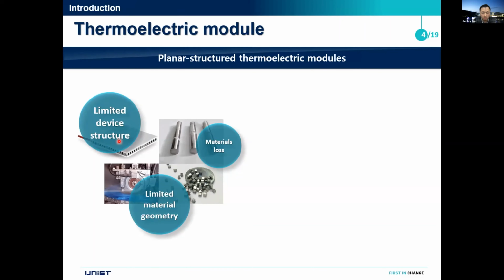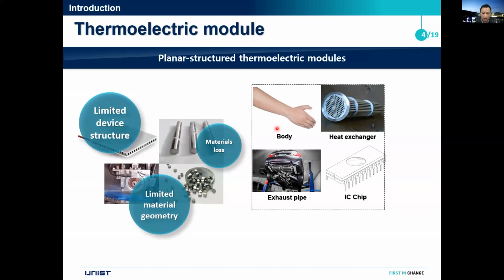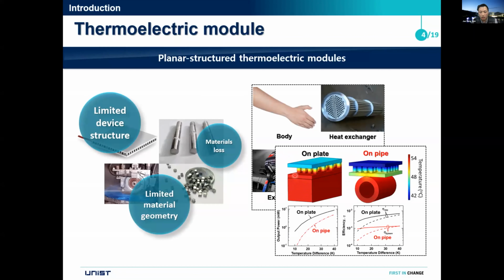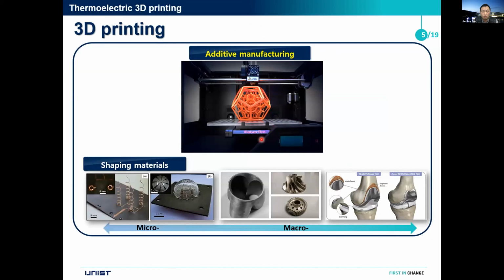But in the real world, most heat sources are not planar. They have freeform surfaces like curved structures, such as our body, a heat exchanger, and an exhaust pipe, which are already curved. And in our lab simulation, you can find a huge difference in the thermoelectric energy conversion efficiency between the case where the planar structure thermoelectric module is mounted on a planar heat source and on a pipe. Their conversion efficiency difference is more than 1 order of magnitude. So we need some new process for device engineering of thermoelectric devices.